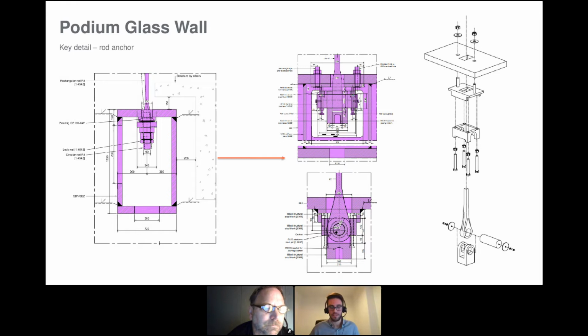So we had to move the detail to something that is less dependent on a product, like the bearing was, but a bit more intuitive probably from a structural point of view. What we had at the end was this rod eye end with a pin, which is then connected back to the top flange, in this case of the bottom beam. Therefore the rod is still ensuring the same rotational capacity out of plane, but it's just working in a slightly different way in how it's connected back to the structure.